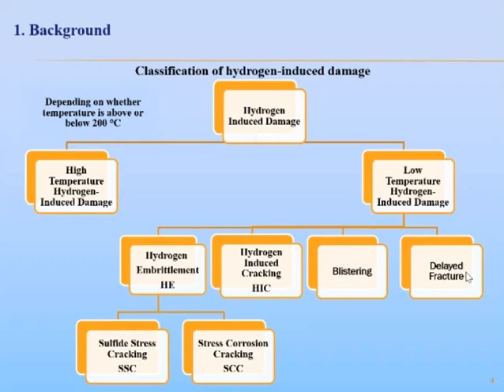In carbon steels, hydrogen reacts at high temperature, higher than 200 degrees Celsius, with carbon to give methane. This phenomenon occurs mainly at the surface of carbon steels, causing decarburization. And if it occurs internally, methane is trapped like hydrogen in hydrogen-induced cracking, creating internal cracks and reducing fracture toughness, fatigue, and creep resistance. This type of damage is often called hydrogen attack.